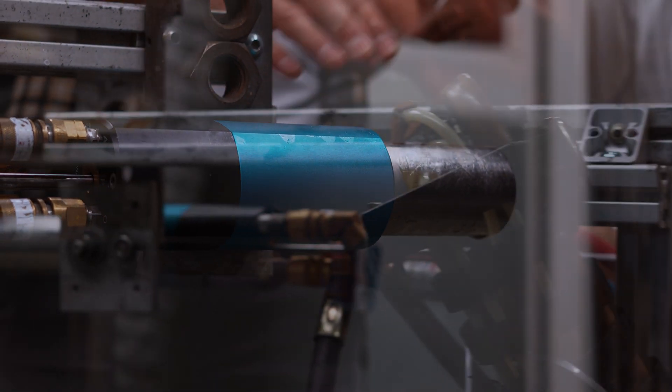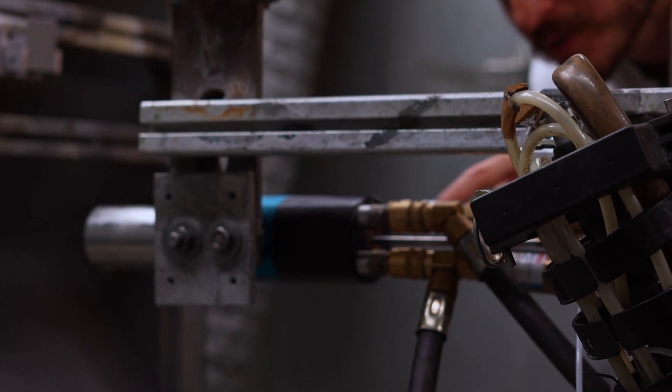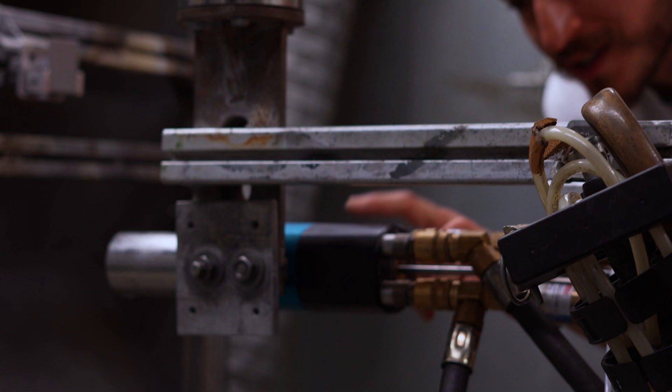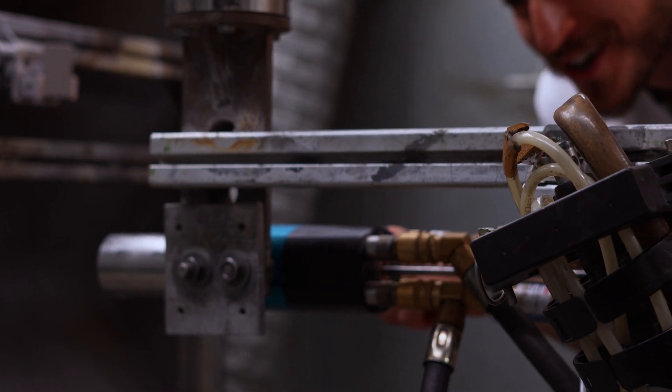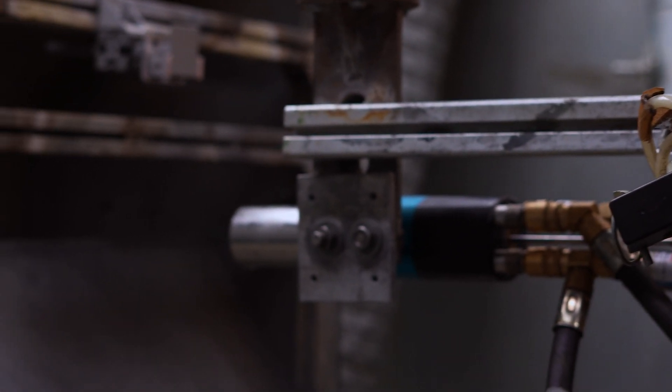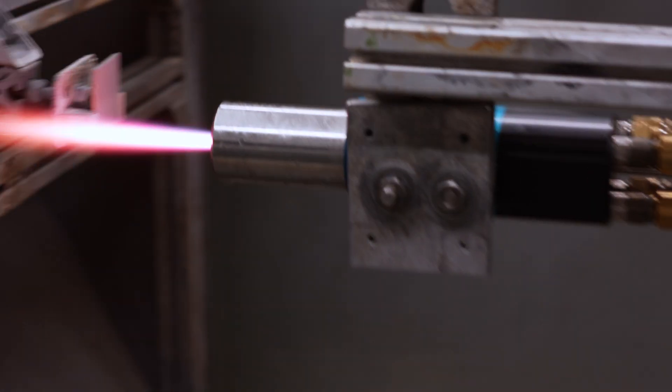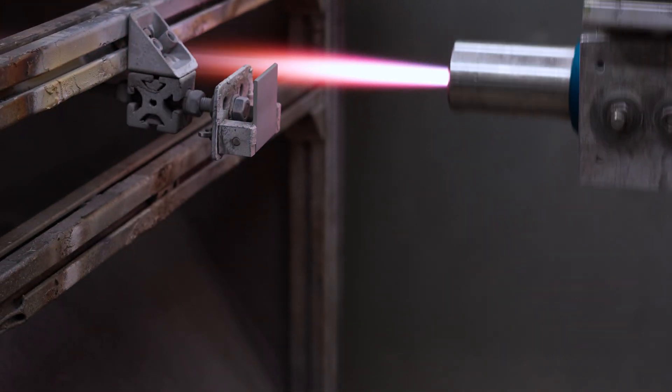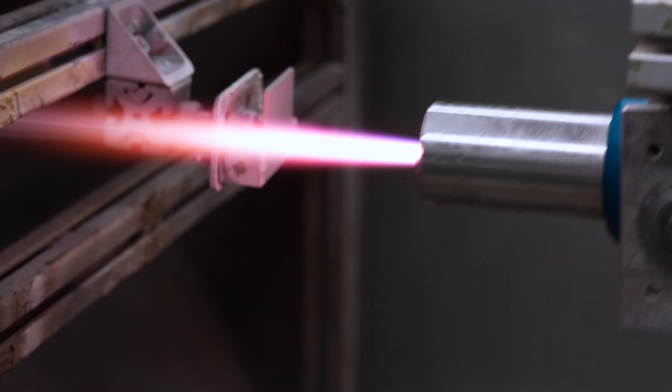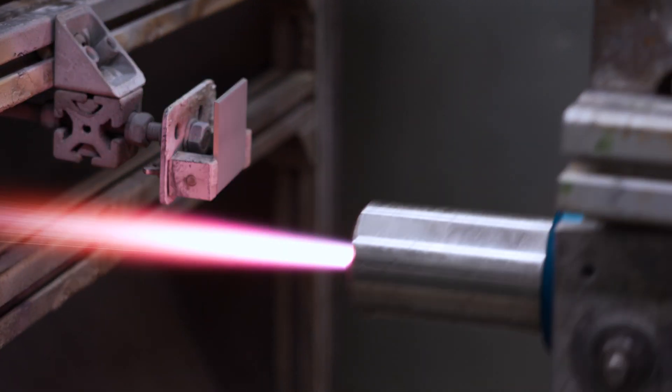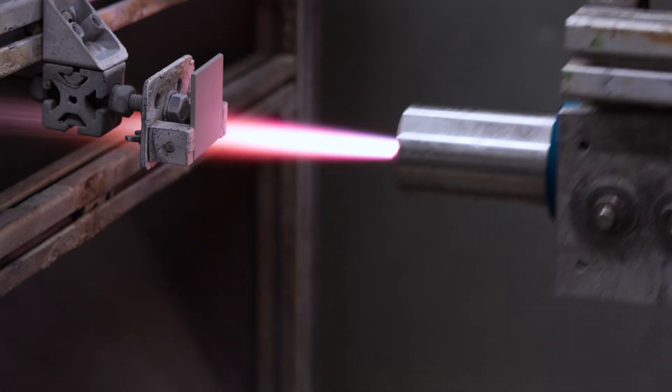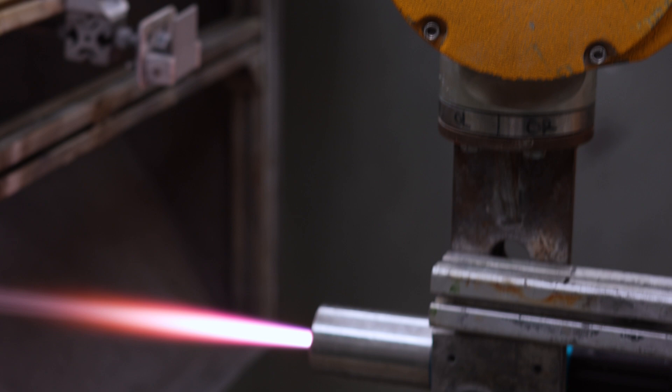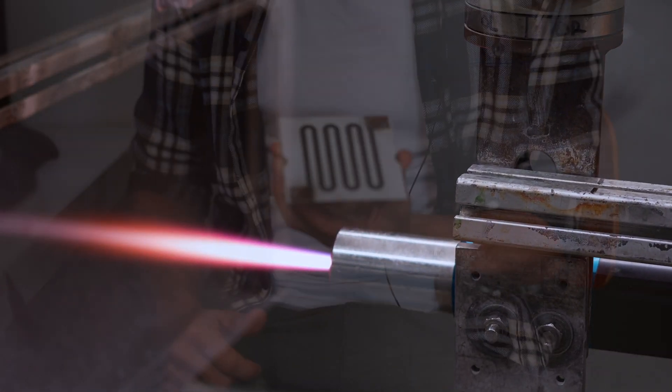And you'll see the process in a moment. The filament will burn off as explained earlier and we'll apply our coating on a substrate. In the process we burn off the binder material and then the dispersed material will be molten in the flame. And we can apply that molten material on any surface basically in order to create a thin and very homogeneous coating.